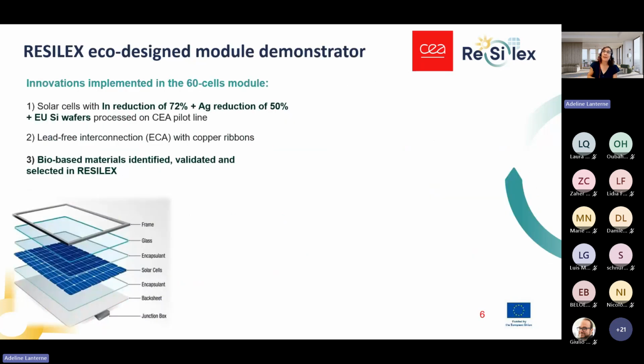Finally, in the project, we had another important result where we implemented this innovation in a 60 solar cells module demonstrator. For that, we implemented the results where we reduce indium by 72%, the approach where we reduce silver by 50%, and we combine this with a European silicon wafer, all processed on a pilot line. This was then interconnected with a lead-free approach, which is ECA with copper ribbons, and we combine that with bio-based materials that have been identified and validated in the project.